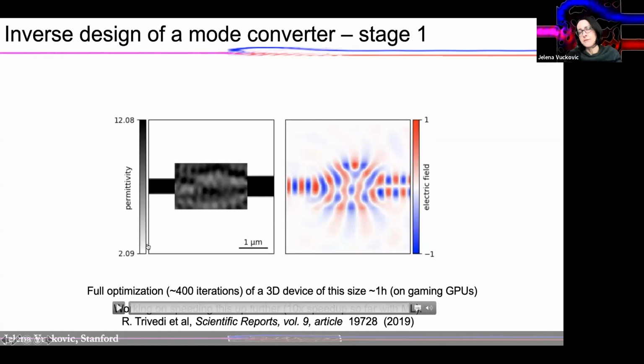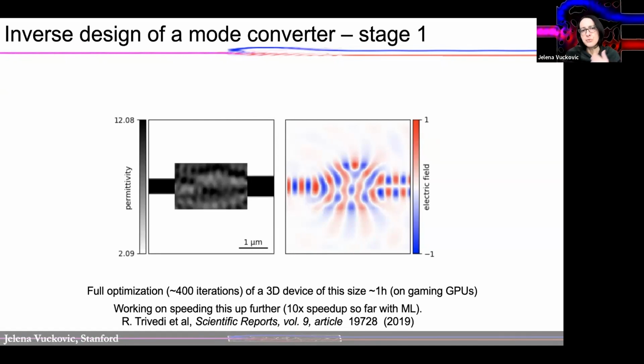And when we started this, we picked some footprint which is much, much smaller than the traditional one, but we didn't really know whether there was a solution. So you run optimization, and if there is a solution, you basically end up in some local optimum, and you stop when you satisfy the figure of merit, which again includes efficiency and robustness to errors and so on. And I should point out that although you see 2-dimensional plots here, all of these optimizations are fully 3-dimensional. We just constrain the pattern in a 2D plane because that's simple to fabricate. But if you can fabricate arbitrary 3-dimensional structures, you can optimize the pattern in 3 dimensions.